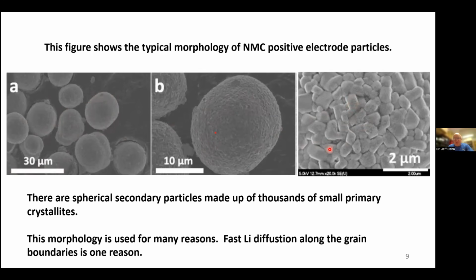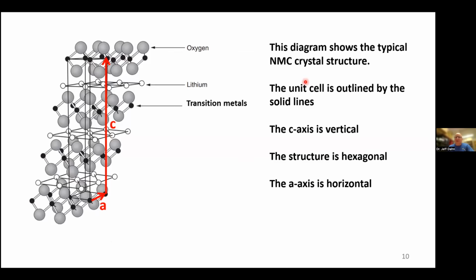And this morphology is used for a number of reasons, but one of them is to get fast transport of lithium from the surface into the middle of the particle where it is stored. The lithium can travel more quickly along the boundaries between these primary crystallites. So fast lithium diffusion along the grain boundaries. Excuse the spelling error there. So why does this microcracking occur?